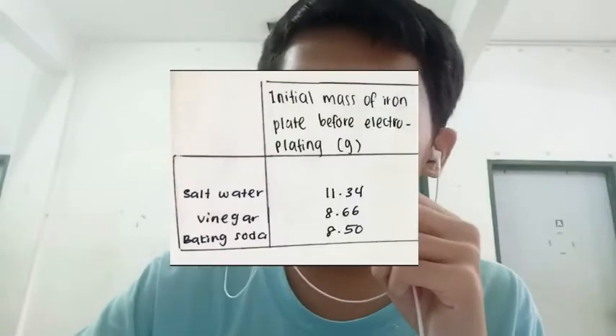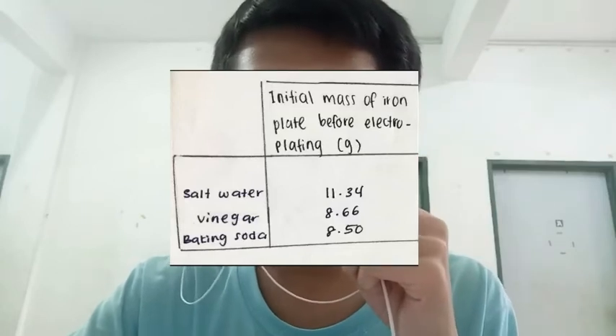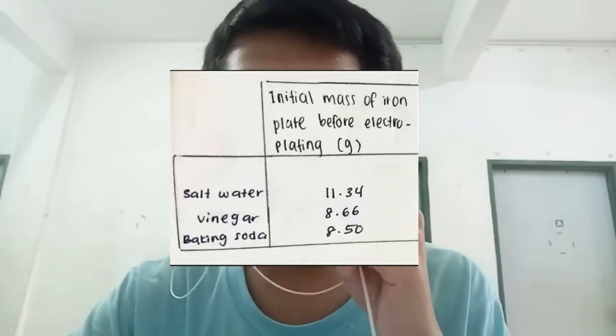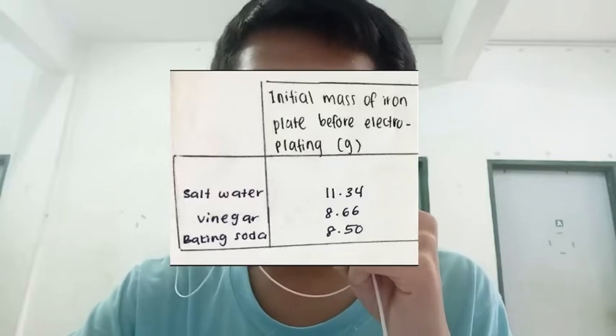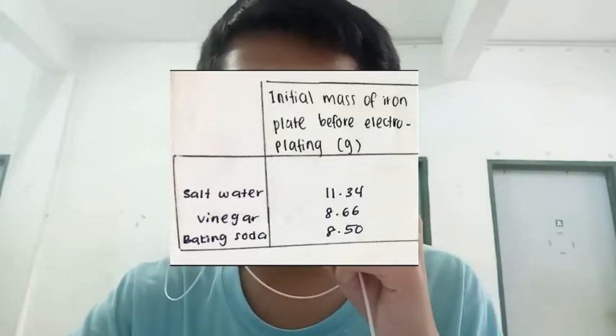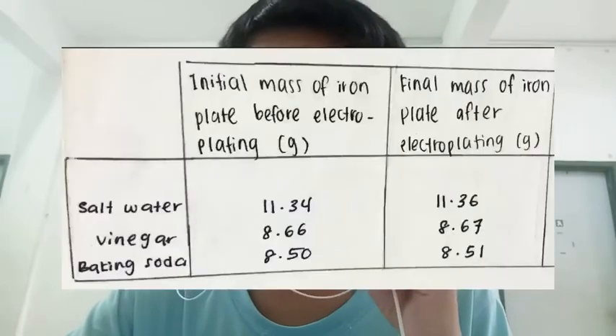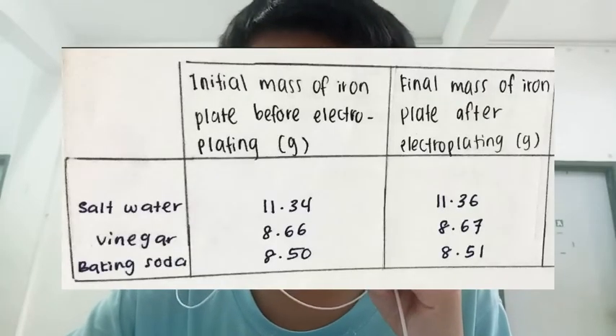So let me tell the results that we obtained from the experiment. First, the mass of the iron plate before being immersed in salt water, vinegar, and baking soda electrolyte are 11.34, 8.66, and 8.50 grams respectively. Next, the mass of the iron plate after being immersed in salt water, vinegar, and baking soda electrolyte are 11.36, 8.67, and 8.51 grams respectively.